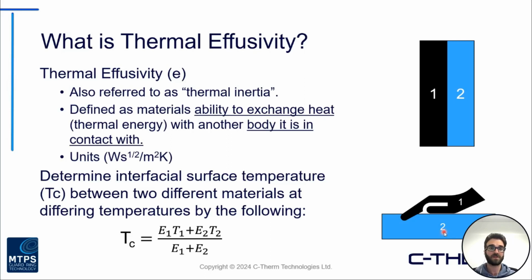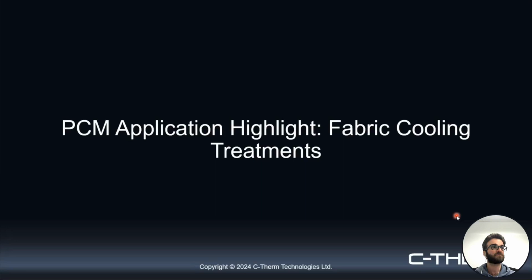Even if those two samples are left out at room temperature, so they're technically both the same temperature, let's say 23 degrees Celsius, if you touch both of those, the metal is going to feel extremely colder, but that's related to what's actually occurring at the interface upon contact.